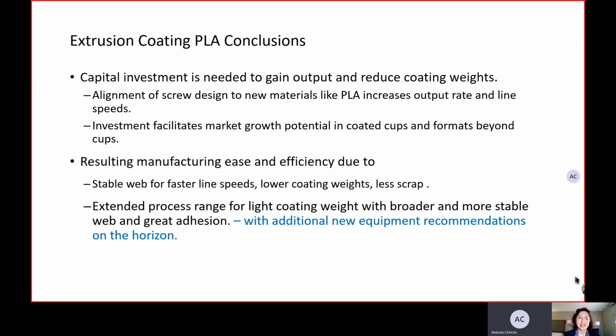So, capital investment is needed to gain output and reduce coat weights for PLA. The alignment of that screw design to new materials like PLA will increase that output rate, and it keeps that melt temperature. It doesn't add too much shear. It doesn't add too much melt temperature to the point where you're compromising your polymer integrity. This investment would facilitate market growth potential in coated cups, beyond cups, so into trays. So we really see it as an investment to grow.